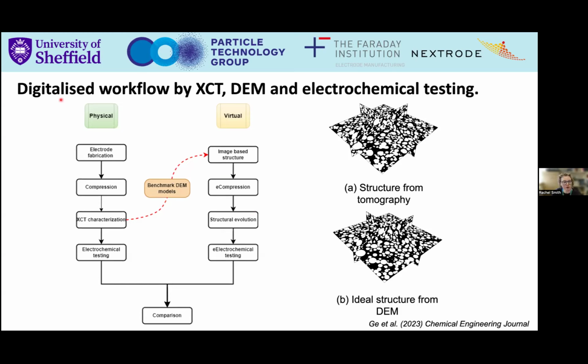So we've proposed this digitized workflow and published this in 2023. Basically what we're trying to do is create a workflow for people to follow, including us, which looks at the way we can benchmark or compare our model with our simulation, and basically validate our model. And so here we have our physical methodology. We create our electrode, we compress it, we characterize the structure of it using X-ray CT, and then we do electrochemical testing. That basically gives us performance. But when we do our virtual, we can do our X-ray CT and import that in here. So also do compression, look at our structural evolution, do our electrochemical testing simulations, and then do that comparison, basically.